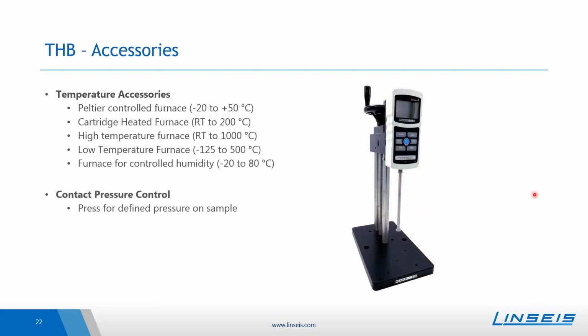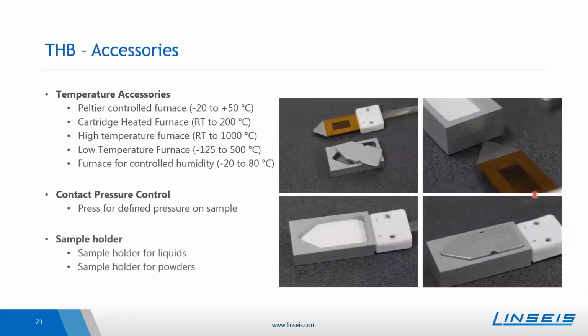For a well-defined pressure onto the sample, there's also a contact pressure control available so that one can measure also thermal conductivity in dependence on the contact pressure. There are also different sample holders, one for liquids and one for powders. For powders, there's a special designed sample holder available where you fill in the powder, put in the sensor, and one can then also compress the powder for the measurement.